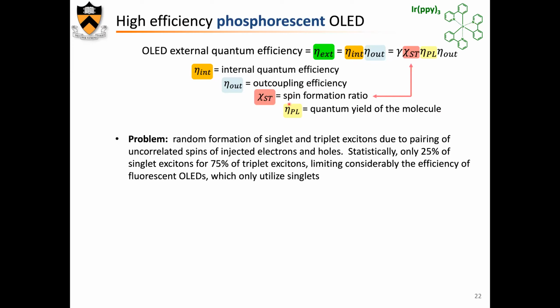Let's look at the spin formation ratio. The problem here is that when you inject electrons and holes from the two contacts of the molecule, you have a random formation of singlet and triplet excitons due to the pairing of these uncorrelated carriers. And statistically, you only have 25% singlet excitons and 75% triplet excitons. And that, of course, limits considerably the efficiency of the device, because only the 25% of excitons can give you light.